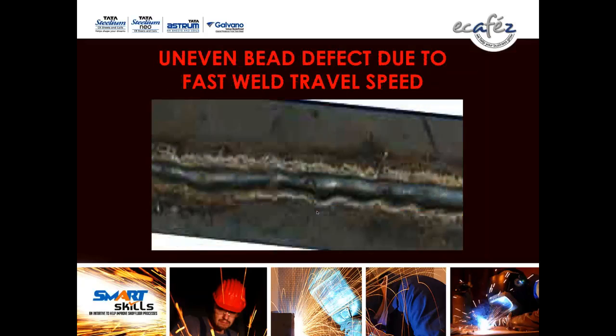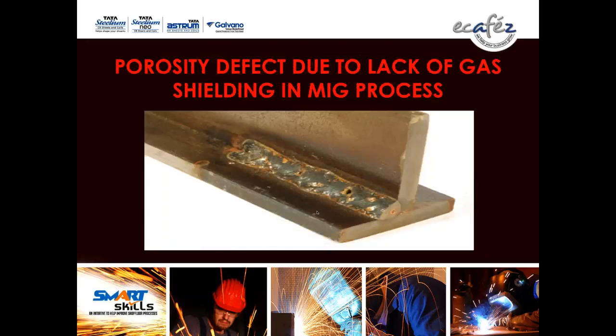Uneven bead defect due to fast weld travel speed. In MIG process, if you go with excessive high welding speed, you can see the results in the pictorial view: uneven welding bead and lesser welding strength. This is called porosity by MIG process. This is due to lack of gas shielding. It may be for low rate of gas flow, or it may be for lack of gas in the cylinder. This is the porosity that should be avoided in MIG welding.